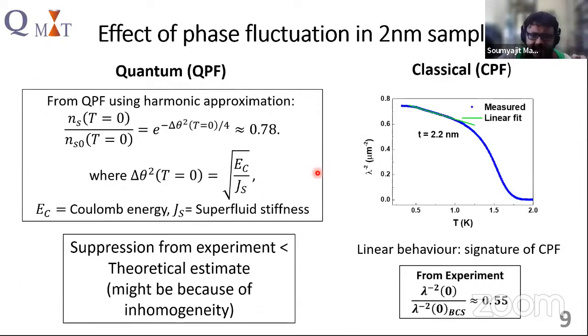So the mismatch in the theoretical and the experimental value might be because the inhomogeneity in the lowest thickness sample was not included in the calculation, although the value is in the same range. And in the temperature variation, the 1 by lambda square also followed a linear behavior, which follows the classical phase fluctuation calculation.